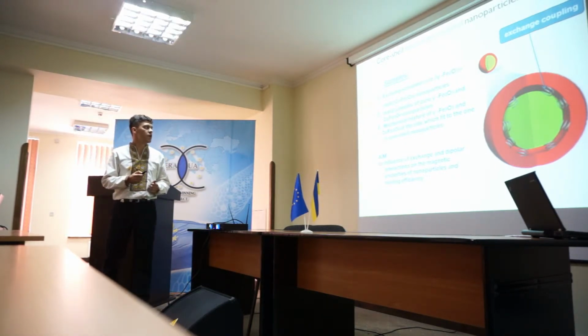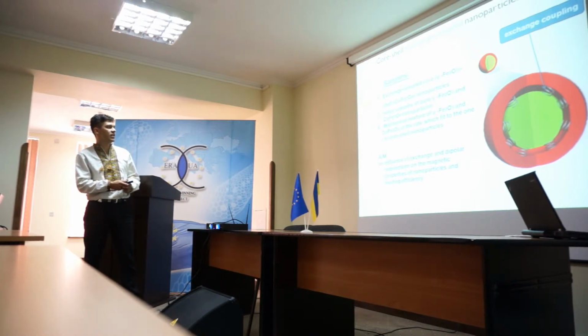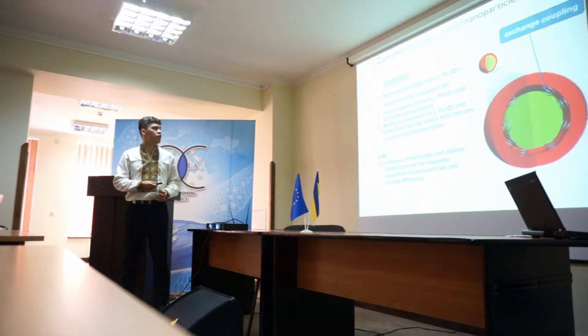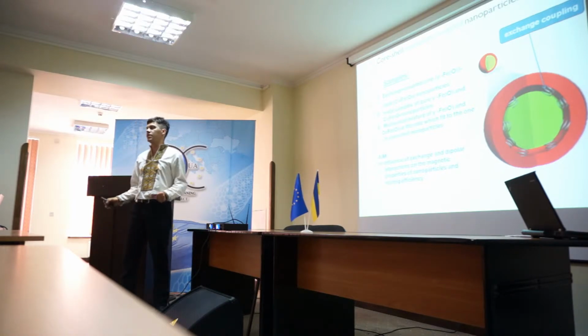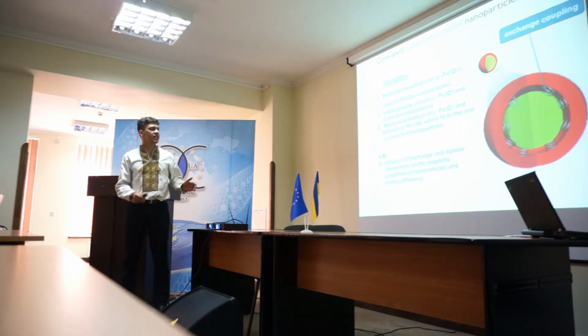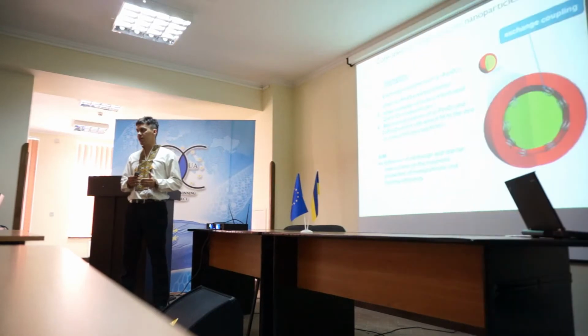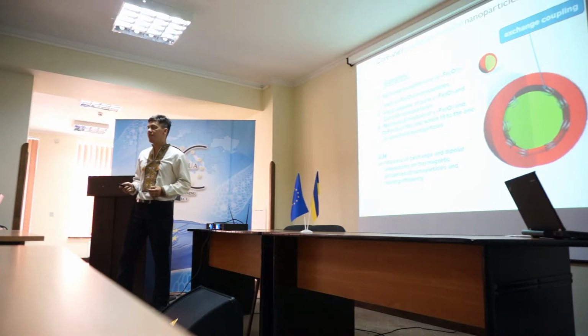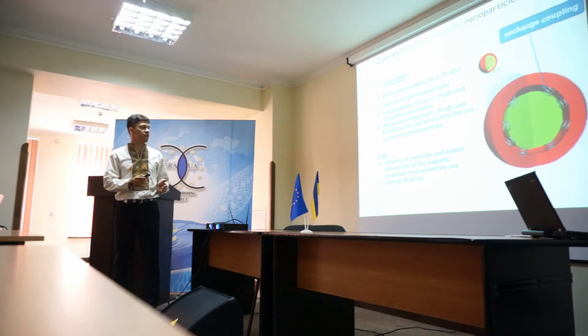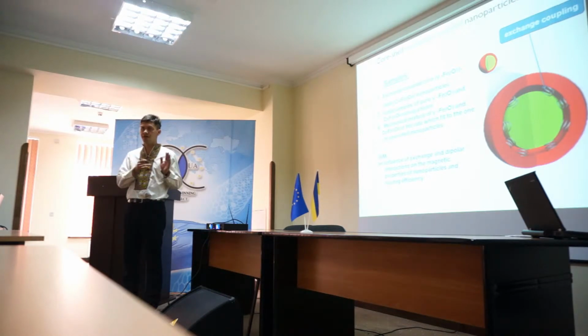For this investigation, we made magnetic nanoparticles. We made the pure magnetic nanoparticles and cobalt ferrite nanoparticles. These are the initial samples. The next sample is a mix of these nanoparticles, and the last sample is the core shell nanoparticles with a magnetic core and cobalt ferrite shell. The aim is to understand how the exchange and dipolar interactions influence the heating efficiency and magnetic properties of these systems.